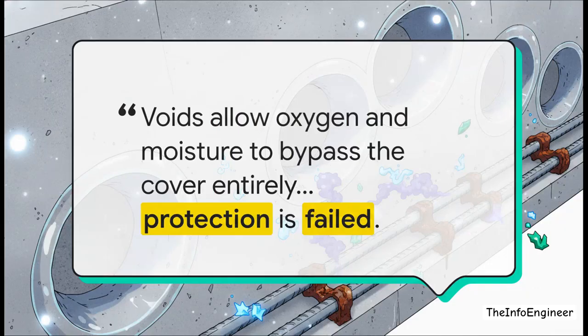So the crucial point here is simple, but honestly devastating. It doesn't matter if an engineer specified 3 inches of concrete cover over the steel. It just doesn't. Because if that cover is full of honeycombed voids, it's completely useless. Those hollow spaces act like superhighways for oxygen, moisture, carbon dioxide, and chlorides to bypass the dense concrete cover entirely and drive straight into the heart of your reinforcement. Basically, your protection has failed before the building is even finished.